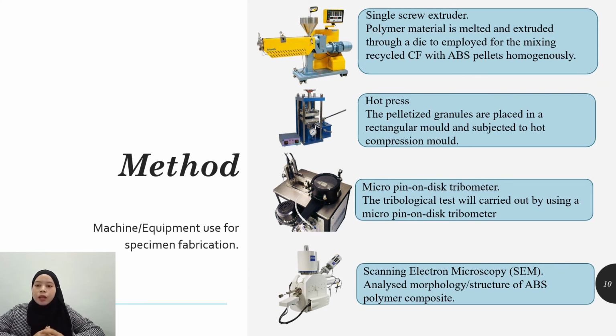And the last slide will show you the machines or equipment used for specimen fabrication. Firstly, the single screw extruder, where the polymer material is melted and extruded through a die, employed for mixing the recycled carbon fiber with ABS pellet homogeneously. Second, the hot press, where the pelletized granules are placed in a rectangular mold and subjected to hot compression molding. Third, the micro pin-on-disk tribometer will be used to test the tribological properties. And last, the scanning electron microscope is used to analyze the morphology or structure of the ABS polymer composite.